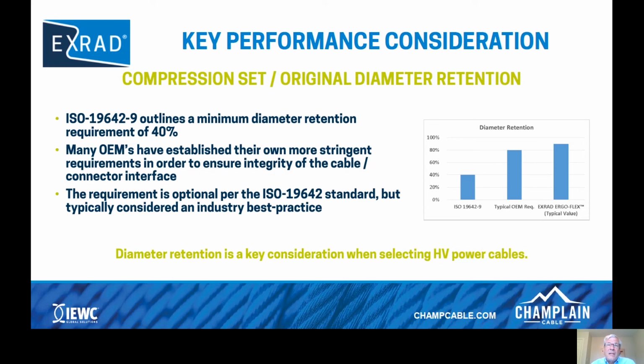And I should mention that the ISO 19642-5 does not have this, but really it should, because there are connector interfaces on unshielded high voltage cables as well. And you can see the last column on the right, the X-Rad ErgoFlex, the typical value of that is in the low 90%. Now, a key takeaway to this is diameter retention is a key consideration when selecting high voltage power cables.